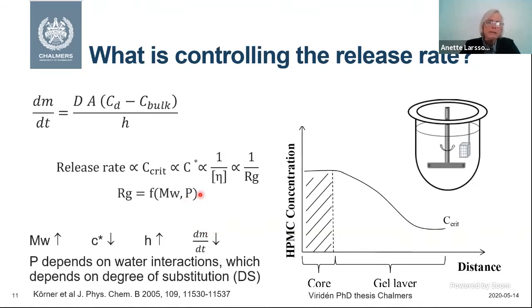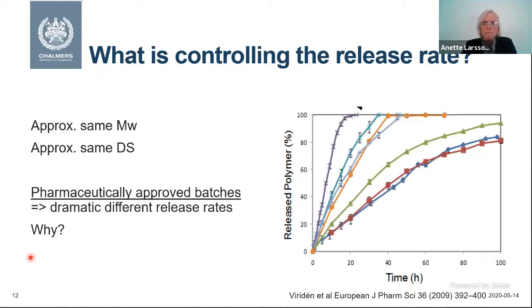The persistence length is also controlled by the polymer properties. In this case, the interactions with the water will rule it, and then it comes to the degree of substitution. So this can explain why the molecular weight and the degree of substitution, which has been shown for a long time, is controlling the drug release rate from this type of formulations.